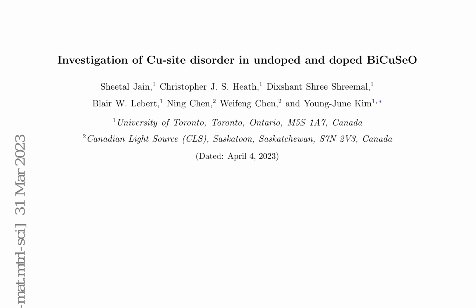data of undoped BiCuSeO. Temperature-dependent XRD data for undoped BiCuSeO is presented in Figure 2a, where the color map shows the intensity of XRD data as a function of temperature. The colored lines of higher intensity represent the XRD peak positions from the sample. As temperature increases, the peak position shifts to lower angles, indicating an increase in lattice constants due to thermal expansion. No discontinuity is observed in the data over the entire temperature range, signifying that no phase change occurs in this range. The Rietveld refinement profile for XRD data of undoped BiCuSeO at 573 K is shown in Figure 2b, for the 2 theta range of 20 to 60 degrees.